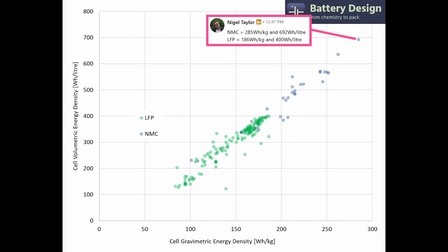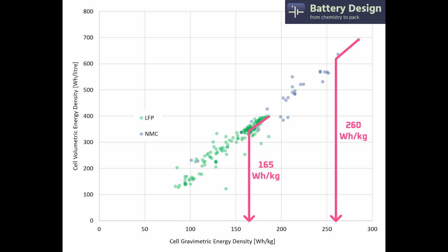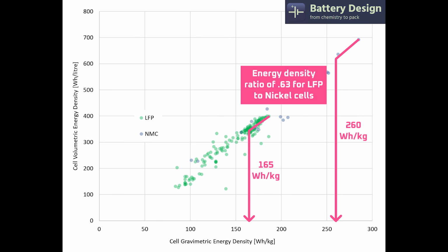NMC prismatic cells reach about 285 watt-hours per kilogram, whereas LFP prismatic cells max out at around 186 watt-hours per kilogram. Let's say that more realistic figures for usable energy density would be, respectively, more like 260 watt-hours per kilogram and 165 watt-hours per kilogram. That's a ratio of 0.63 for LFP to NMC.